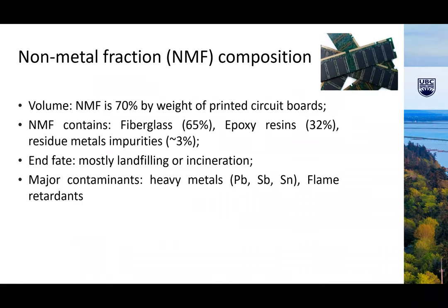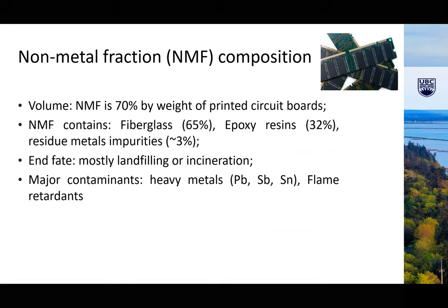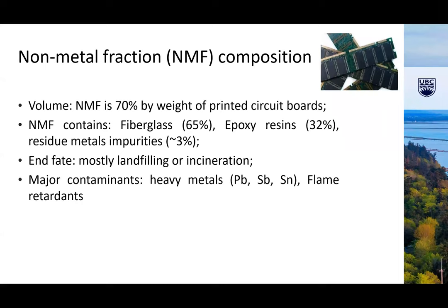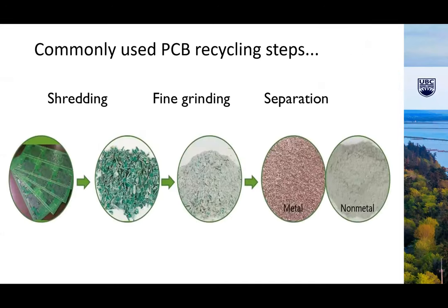So majority of material is in that form. Fiberglass, 65%, epoxy resin, 30%, and residual metals that can vary from 3 to 5%. And as I mentioned, if not taken care of properly, it will end up in landfills or incineration. Commonly for recycling, we would shred, we will fine grind if we need to unlock those metals, and the focus is to recover metals. Non-metal fraction, by the time we grind to extract locked metals, we have pretty much a very messy mass of the materials, which is useless if we do this in a sequence like that.